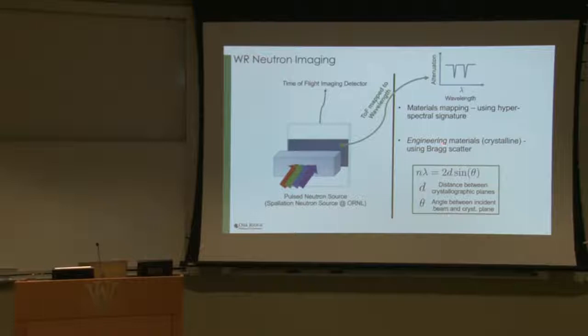Because if you have a crystal and you have an incident neutron beam, it'll scatter away the beam depending upon Bragg's law. Whenever n lambda is 2d sine theta, where d is the crystallographic spacing, a scattering event occurs. And so that can help. So you can start thinking of using this type of instrument to look at crystalline materials. Those are the two big application areas that we're thinking about while thinking about time of flight neutrons.